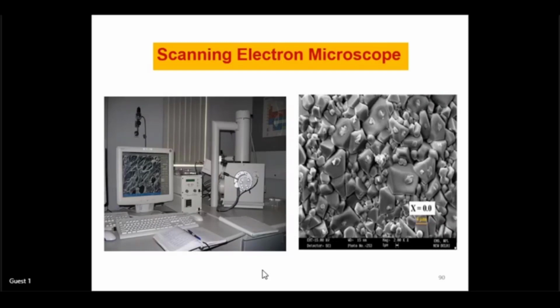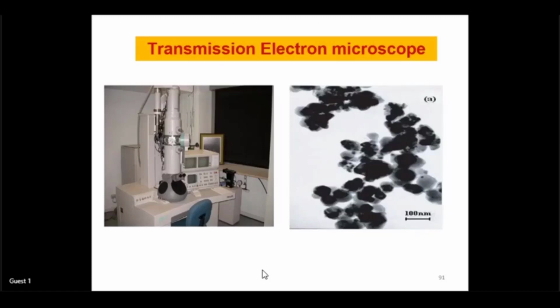So various software are also used to test the surface morphology and to check the grain size variation. Fine. So I mentioned for nano, this TEM is used, and on the left hand side a transmission electron microscope is shown. Photo of that. And on the right hand side, the actual photograph, the transmission electron microscope image is shown. And if you see the scale, it is 100 nanometer. So you can see few particles are larger and few are lower than 100 nanometers. So they are not uniform, but you can see non-uniform particles formed, and they are distributed over the surface.